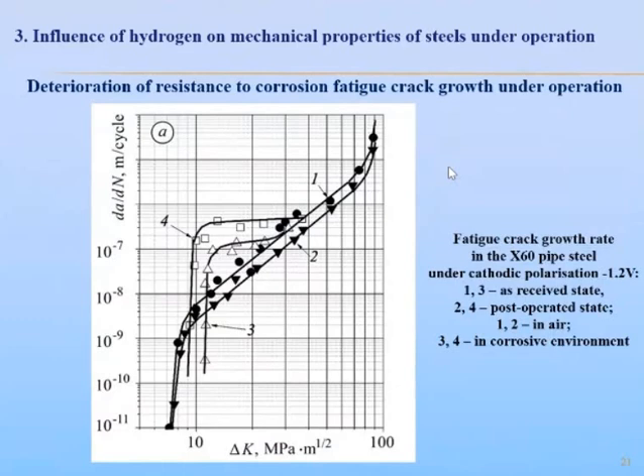Here you can see another example showing deterioration of resistance to corrosion fatigue crack growth under operation. And cathodic polarization of steel in corrosive environment, causing its hydrogen charging, leads to an increase in fatigue crack growth rate, more intensively for operated damaged steel in the medium amplitude region of loading, the Paris region, often with a plateau of rate on the curve. This is due to a combination of mechanisms of fatigue and stress corrosion cracking.